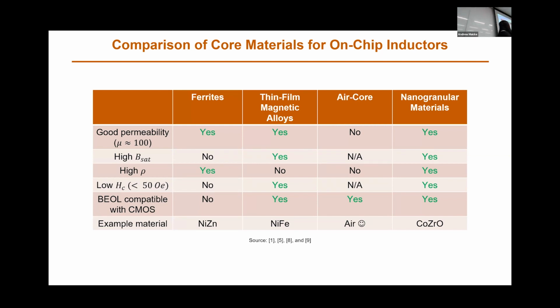People have also tried using thin film magnetic alloys like permalloy, and these are usually okay. They have generally great magnetic properties like good permeability, pretty high saturation, but they suffer from core loss, or specifically eddy currents loss, because these materials are generally very conductive, so lots of eddy currents, and that's really bad. Unlike ferrites, they're actually very compatible with CMOS because you can just electroplate them because they're just metals.